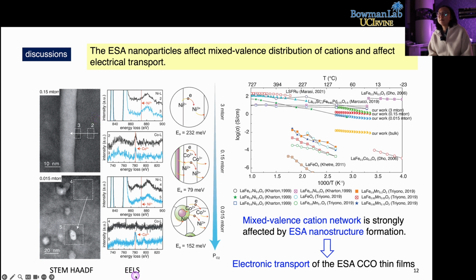So we use STEM EELS to track the valence state change of nickel and cobalt at the interface and in the thin film matrix. At 0.15 millitorr, we found the palladium nanorod. At the interface, we can see the cobalt doesn't have much difference in valence state compared with the thin film matrix, but the nickel does have valence change, especially at the interface. It shows strong nickel 2+. So we can think this palladium nanorod creates a lot of interface rich with nickel 2+ to help the electron hop.